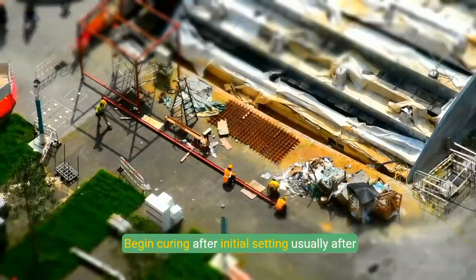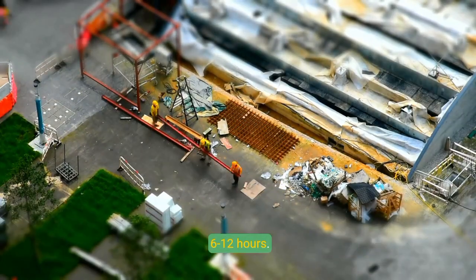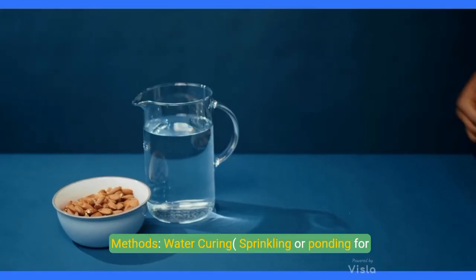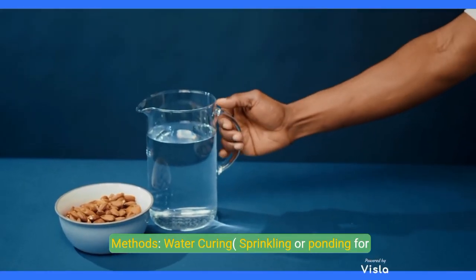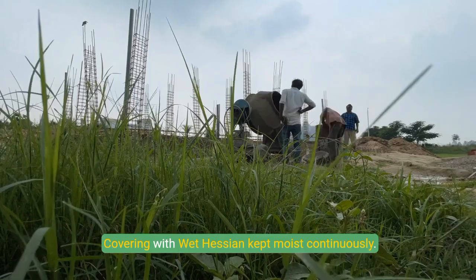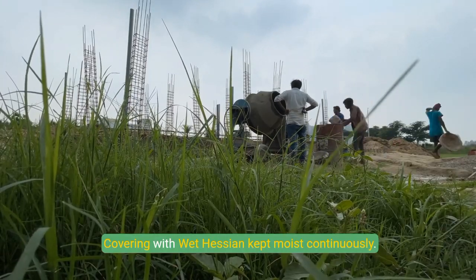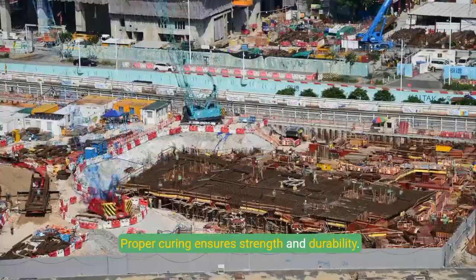F. Curing. Begin curing after initial setting, usually after 6 to 12 hours. Methods: water curing, sprinkling or ponding for 7 to 14 days. Covering with wet hessian kept moist continuously. Proper curing ensures strength and durability.